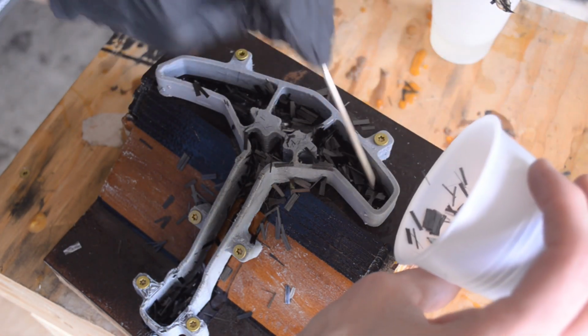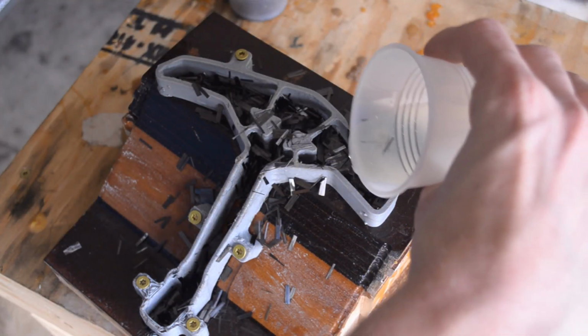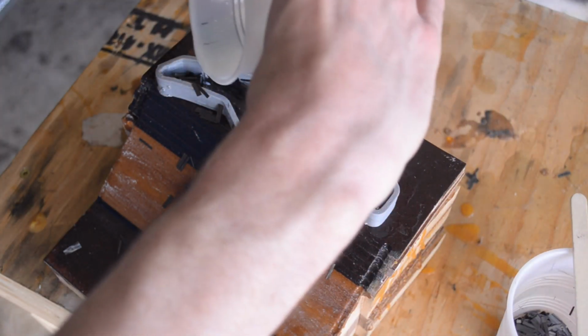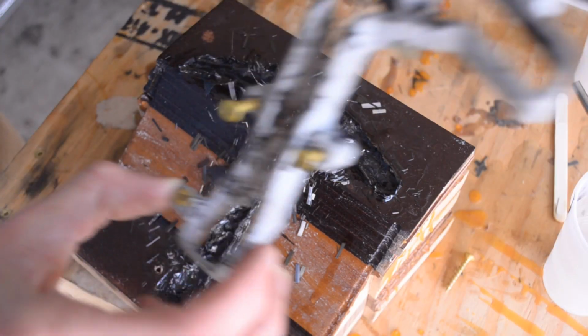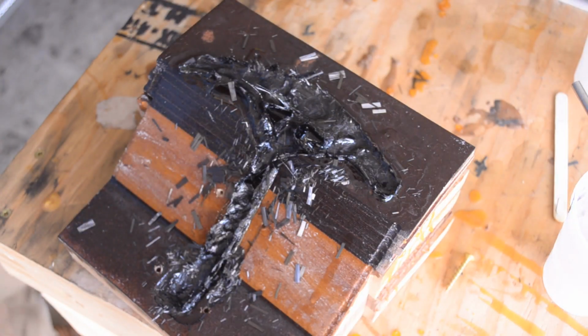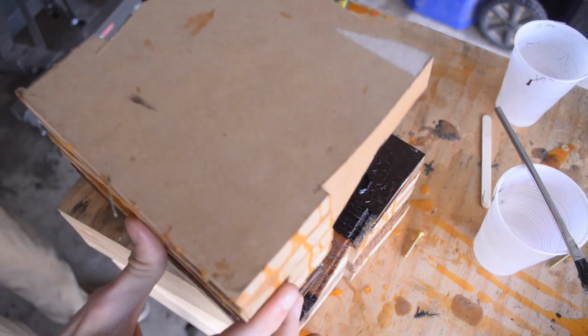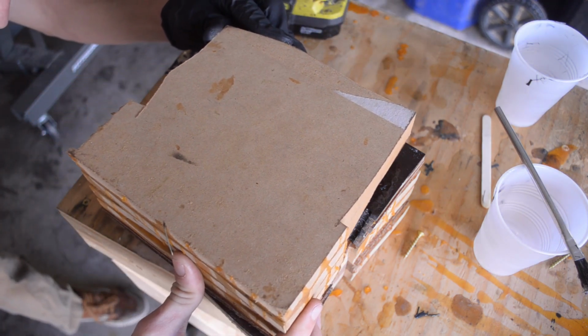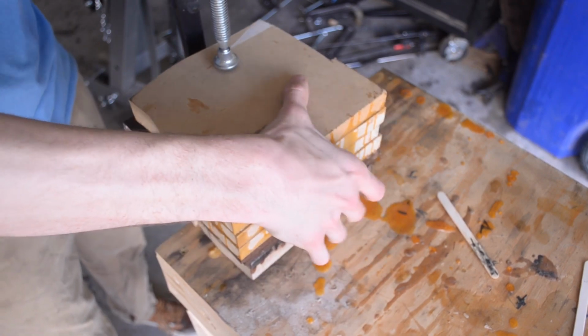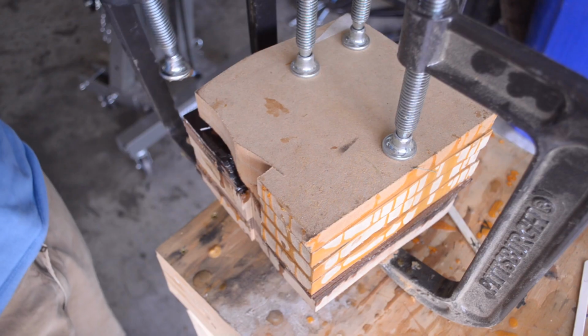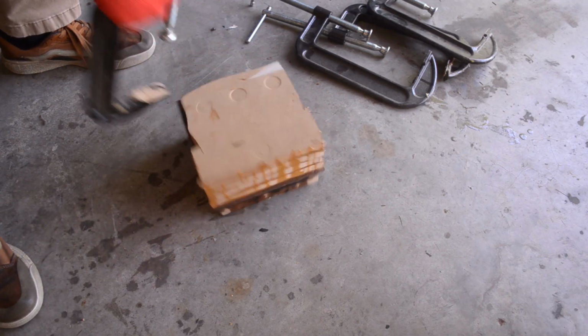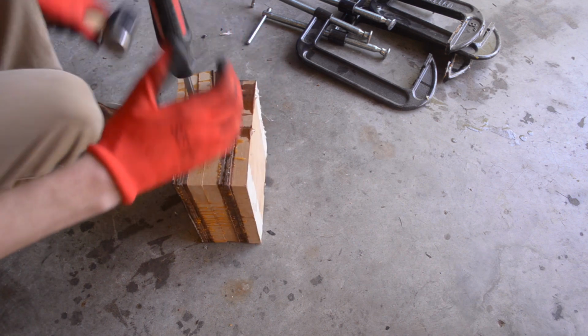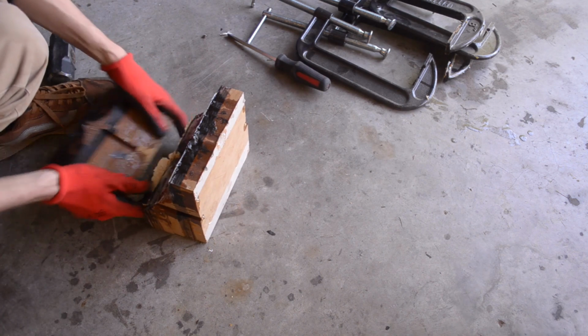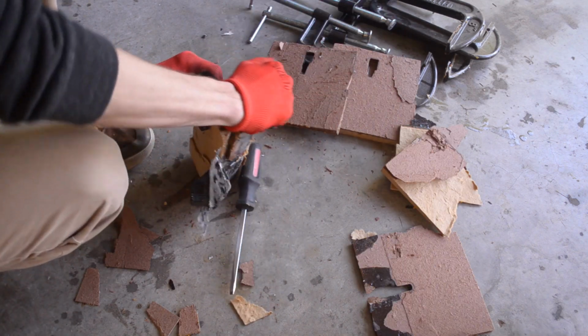And it looks kind of like a mess at this point, but what we're going to do is take the male mold and compress it onto the female mold and really put a lot of clamping pressure on this, making sure that we get good consolidation between the male mold and the female mold, because this manufacturing method really relies upon compaction to get a really high strength, good and viable part. So that's probably one of the most important steps. And then once it's cured, we can go ahead and delaminate the paddle. It just takes a hammer and a screwdriver and a little bit of patience, and it comes right apart eventually.